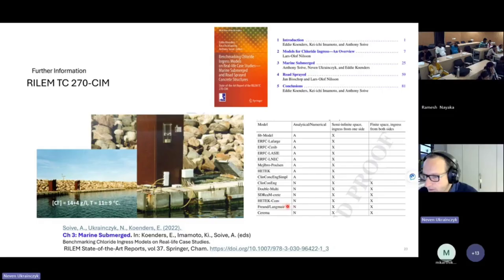I also had here one model, the reaction diffusion model, where I explicitly modeled the chloride ingress by the nonlinear isotherm, Freundlich and Langmuir. So there were analytical models and numerical models. And there were some quite advanced reactive transport models, STADIUM for example, and more advanced analytical models. And there is one very well defined case study from Norway, I think, or Sweden, I'm not sure. I think it was Norway. They did a very well documented case study, and we used that case study to benchmark the models.